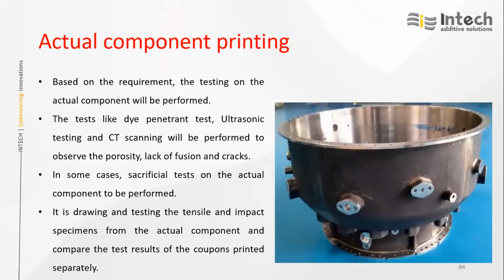Once the qualification step is done, we will print the actual component. Few customers like HAL, BHEL will ask to destroy the actual component and perform tensile and impact testing, because whatever we do otherwise is at coupon level. But with the actual component, if you extract tensile coupons, you get extra confidence.